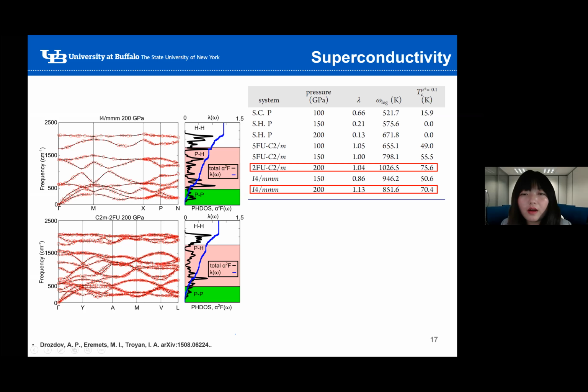The larger omega log in the two formula unit C2/m phase could be because the canting angle results in a larger number of hydrogens that can be found within 2 angstroms of one hydrogen atom, and that increased the frequency of the related modes. For lambda, the major contribution was from the phosphorus-hydrogen interactions and hydrogen-hydrogen interactions, shown in white here. The phosphorus-phosphorus interactions also contribute, but not as much.